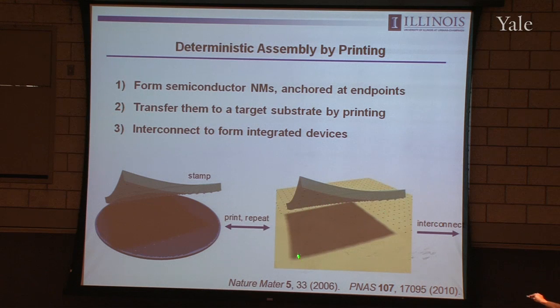and then deliver that stamp down to a target substrate of interest, could be a sheet of plastic, a piece of rubber, and drop off the nanomembranes from the stamp onto this target surface in sort of a massively parallel fashion that will allow you to come back and do this in a step and repeat type of mode to spread out this active material in desired locations on a foreign substrate. You do this as many times as you need, and then the next step in building an integrated circuit would be wire these individual membranes together to make a functional device. And so that's an approach that's worked extremely well for us.